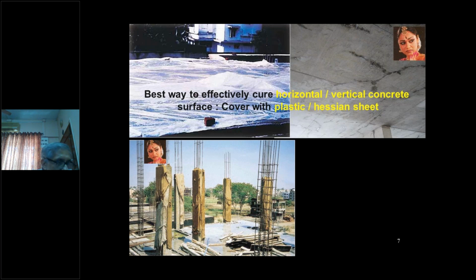Now, no matter what waterproofing you do, it may last you 5 years or 10 years and again you get into problems. So the best solution is to prevent these plastic shrinkage cracks. People often blame the cement for these cracks, and if they have taken Readymix concrete, they blame the Readymix concrete. But cracks do not occur due to both these reasons. Cracks occur due to poor initial curing at the top surface.